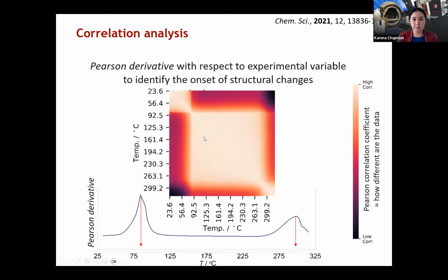And then we can take a differential of this to pull out the temperature at which we start to see changes in that type of data. So the onset of the structural transition.